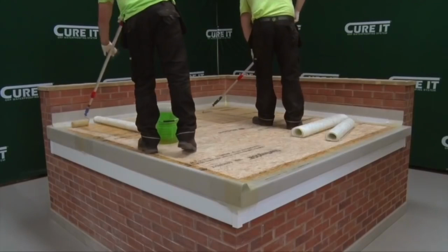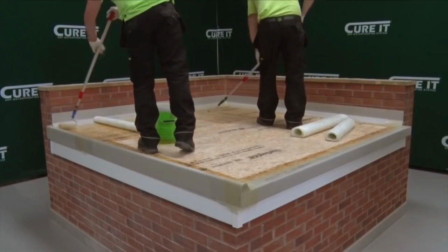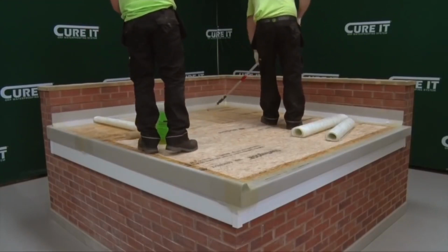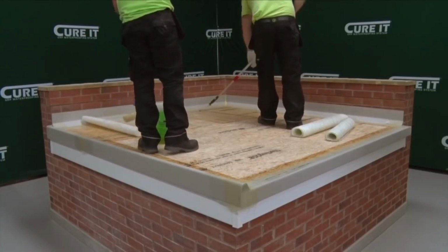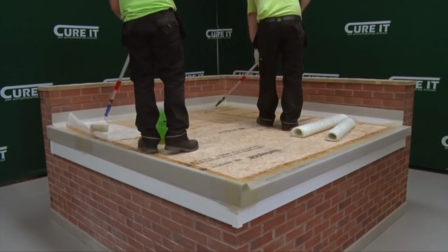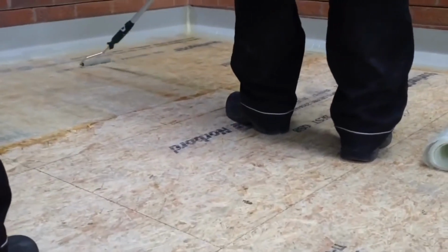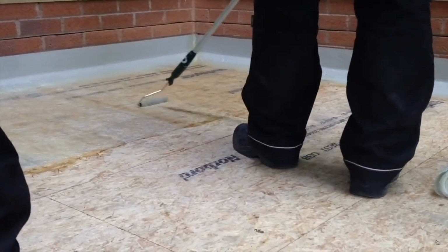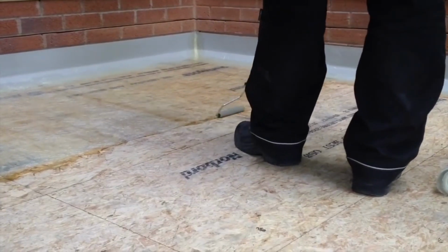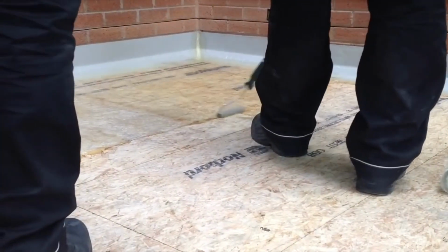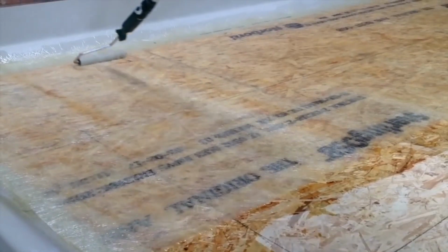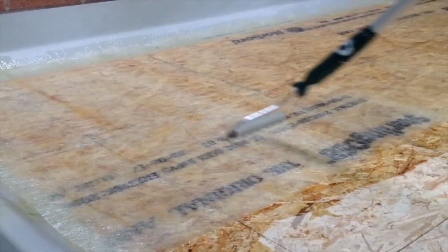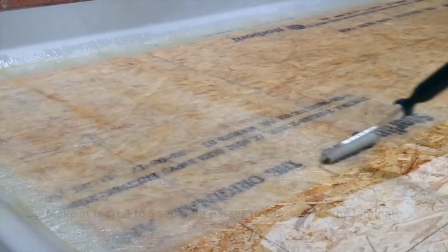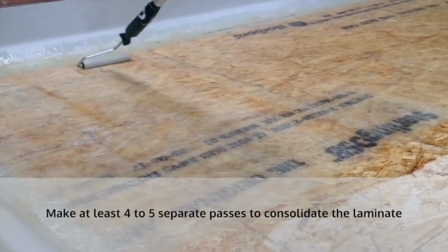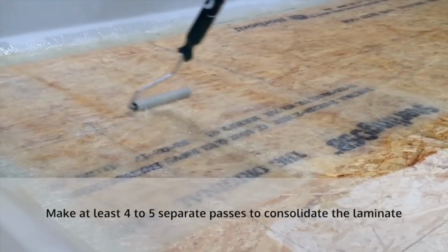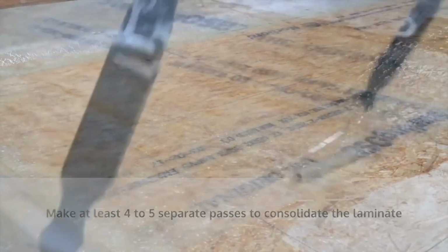As one person continues to apply the reinforcement mat and resin in 1 meter square sections, the second person can start to consolidate the laminate using the paddle roller. This is the most important stage of laminating. It ensures the reinforcement mat is saturated with resin and any trapped air is removed. Roll the paddle roller in a slow, controlled motion over the resin-soaked mat. Make at least 4 to 5 separate passes over the same meter square area until the mat is transparent.